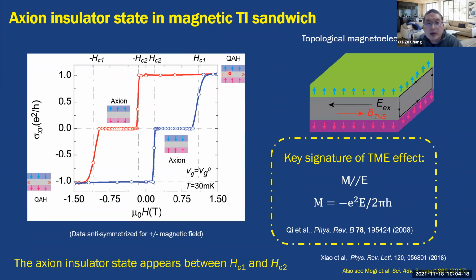We noticed that in the quantum anomalous Hall effect, we could observe h over e squared as the Hall resistance, and e squared over h as the Hall conductance. The reason is each surface contributes e squared over 2h of Hall conductance. Two surfaces will contribute e squared over h of Hall conductance. In this situation, the top surface is e squared over 2h, the bottom surface is minus e squared over 2h. The total Hall conductance becomes 0. This is the Hall result.